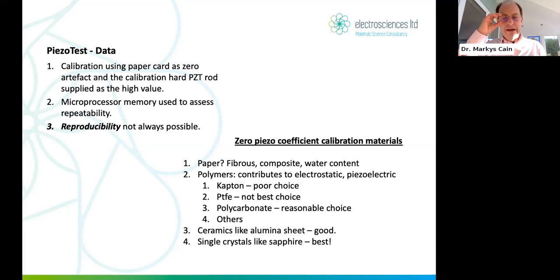But the problem with that is, how do you choose what you choose as zero piezo coefficient? It's a bit more tricky than you might imagine. There are some research reports describing issues like this for another application entirely, and that is due to the electrostatic and piezoelectric induced charges that are generated when you squeeze a dielectric material, making certain polymers which you might think are really good, not so good. For example, Kapton and PTFE, which you might think are really good choices of a material with zero piezo coefficient, no charges being generated when you're squeezing it. That's not actually true. These are not necessarily very good materials to choose.